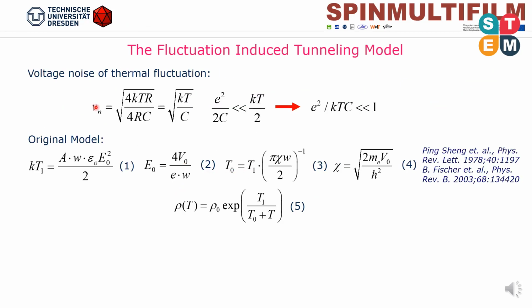The random mean square noise voltage generated in an RC circuit on an ideal capacitor is given by kT divided by the capacity. Therefore, large voltage fluctuations occur when the capacitance of an intergrain junction is small. For a dielectric constant of 40, a barrier thickness of 1 nanometer, and a contact area of 300 nanometers square, the junction capacitance is in the order of 0.1 femtofarad.